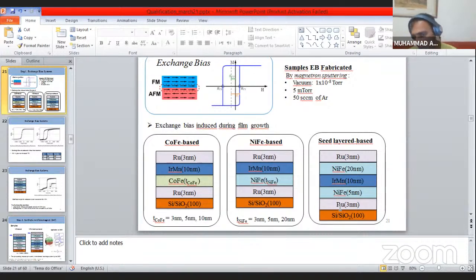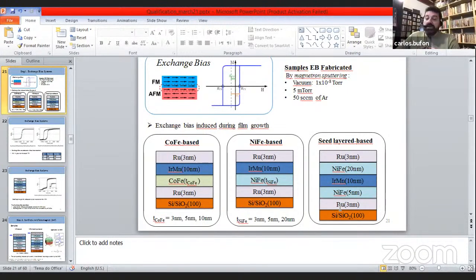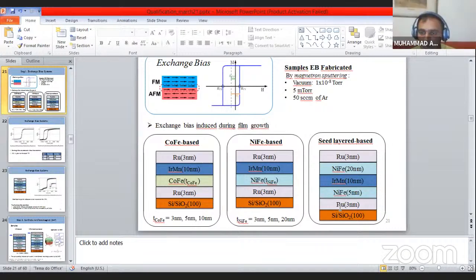We try to grow nickel iron at the bottom, because nickel iron grows as a 111 plane. So we try to use ruthenium, because it has a structure like a 111 plane, so it will grow more smoothly. Okay, so there is also a texturing process. Yes.